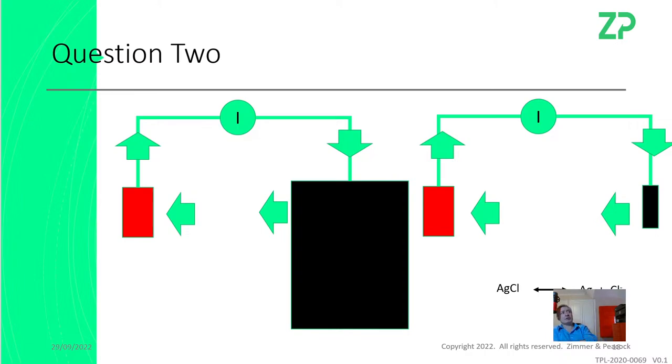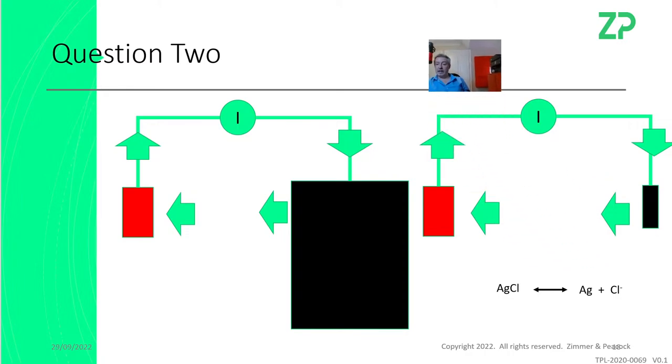Now, when you make an electrode from platinum, basically you don't know what's happening at your counter electrode. And so if you don't know what's happening, you better limit your risk by making it quite large, because you might not have anything that's easily happening, but if you have lots of surface area, then at least the thing that's not easily happening gets spread out over the entire electrode. But when you put something on that counter electrode that you know happens, and it happens quite easily, then you didn't need to have such a large counter electrode.